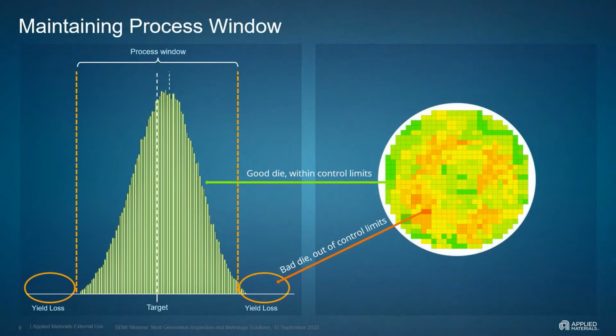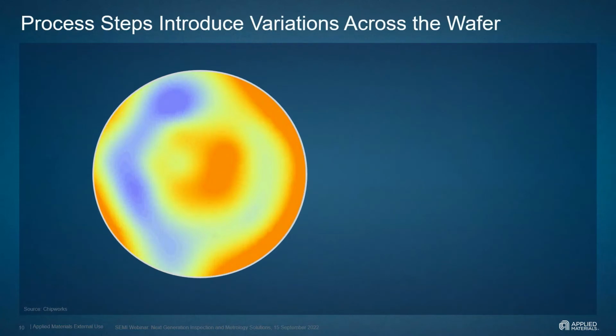Here, for example, these distributions may indicate various performance across the wafer, with the red dots indicating a bad die, which is out of the control limits, and the green dies indicating good dies within the control limits, but still there's a distribution of these parameters. Process steps introduce variations across the wafer, and in this example it's truly across the wafer, but we can also look at other spaces of variations which we need to control.